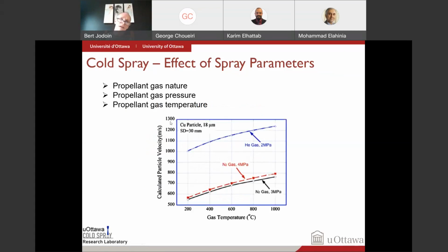Here you have curves of the particle velocity, function of the gas temperature that you use for one specific gun. You can see here when you're using nitrogen at 4 megapascal, that's the pressure and temperature before the gun. As the temperature increases, the particle velocity increases also because you get more thermal energy converted into more kinetic energy transferred to the particles. The effect of the gas stagnation pressure, well, not that much.